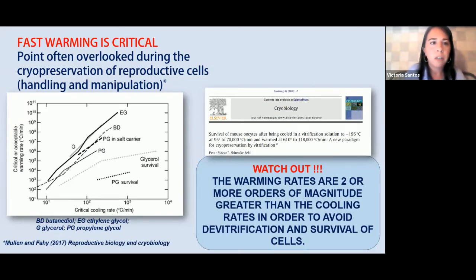Fast warming is critical. This is a point often overlooked during the cryopreservation of reproductive cells. As you can see in this figure, the critical warming rates are higher than the critical cooling rates. They are two or more orders of magnitude greater than the cooling rates in order to avoid devitrification and ensure survival of cells. This was also published and said by Peter Mazur and Seki in this